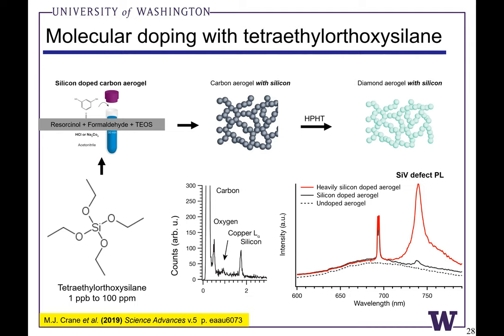So next we started to design experiments where we tried to recover that silicon split vacancy emission by deliberate molecular doping. So this is a very well-known organic molecular precursor. This is tetraethyl orthosilicate that's used to make silica aerogels, often in a laboratory scenario. So we simply added ppb to ppm levels of this organic molecular precursor for silicon into the resorcinol formaldehyde reaction vessel. This is also in the plastic reaction vessel to avoid any etching of silica.